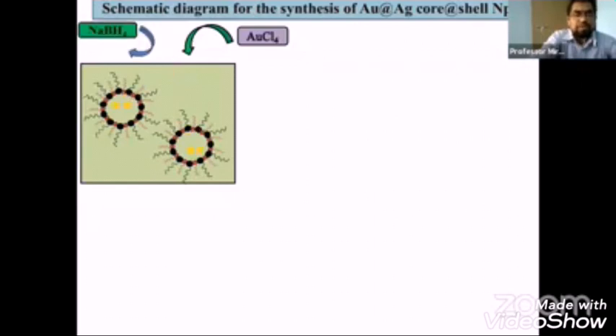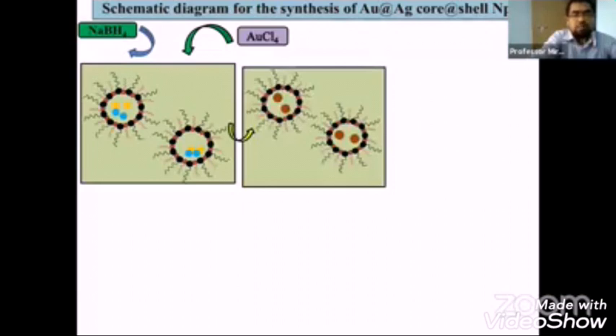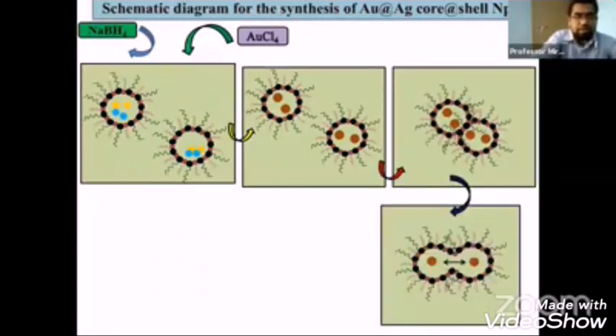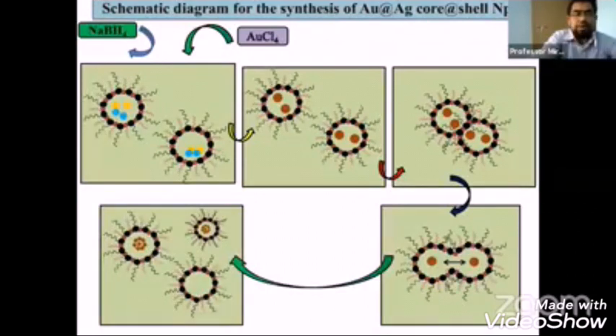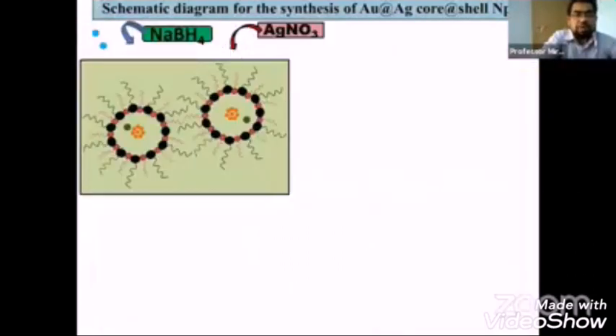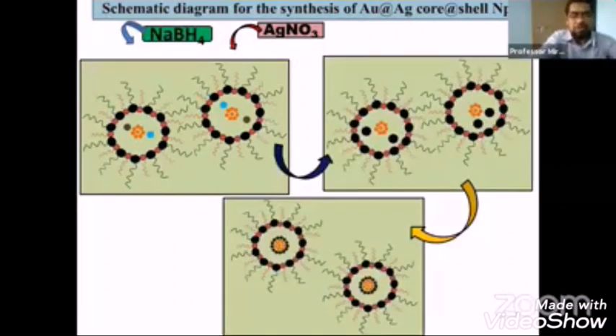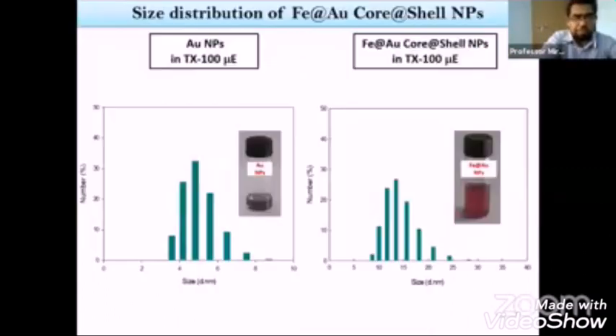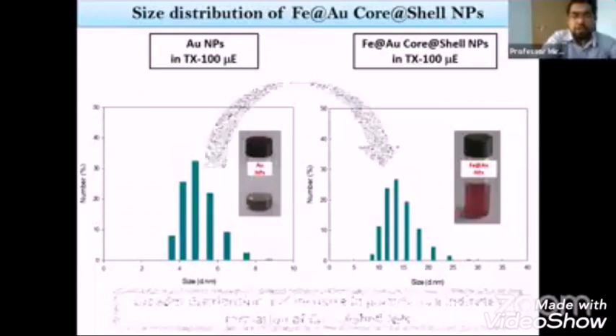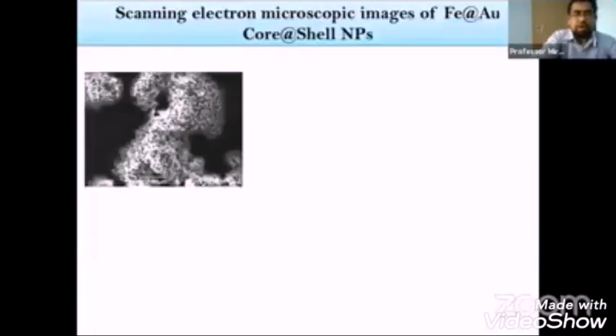At first we add auric chloride, then we add sodium borohydride, and due to the reaction, gold particles are reduced. Then due to the coalescence, you can see several gold particles are produced. Then we did the same experiment for silver and sodium borohydride. Finally, silver particles were produced, and you can see the silver coated gold nanoparticles can be prepared. So this is the DLS measurement. You can see the size and color difference for gold nanoparticles and gold coated iron nanoparticles.